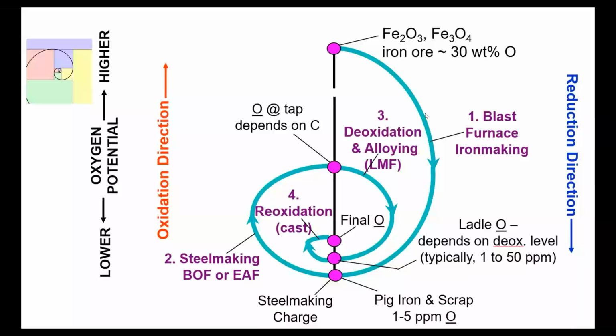So we start by reducing the ore to a very low oxygen content, say single ppm digits. Then we go into something like the EAF or the BOF where we raise it back up, maybe up to like 1,000 ppms of oxygen. Then we go back and do some kind of secondary ladle metallurgy where we bring the oxygen content back down by killing the steel, using aluminum, silicon, something like that, to end up at some kind of low oxygen content.